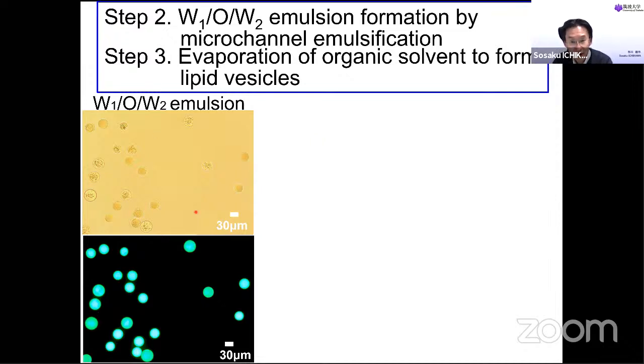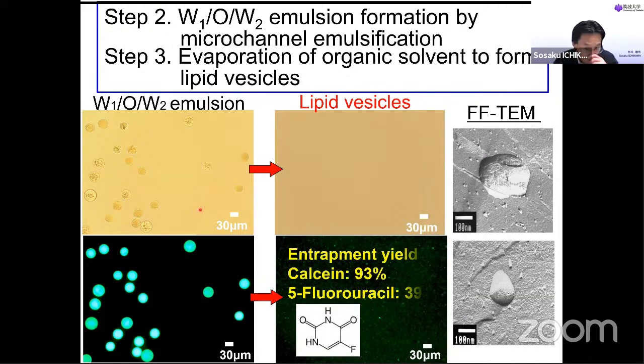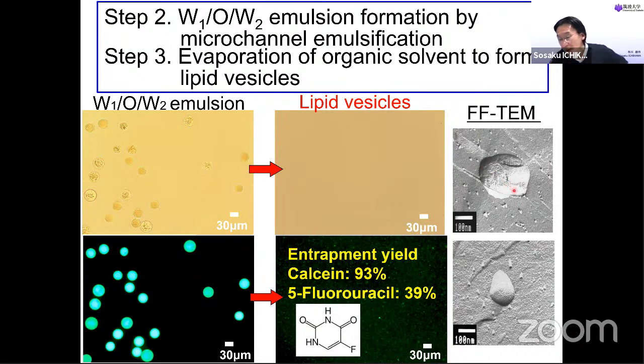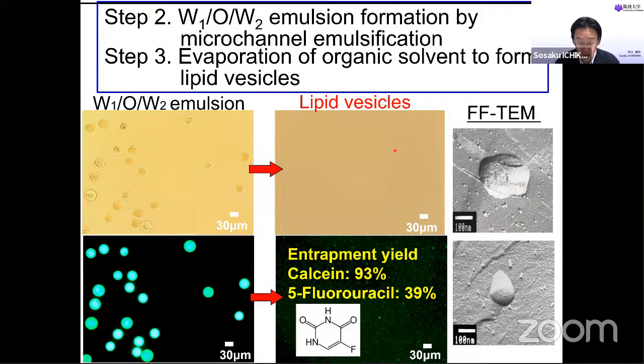This is the W/W emulsion. This is a lipid vesicle. We can observe the lipid vesicle formation by freeze fracture TEM like this. You can see the size of this lipid vesicle. The diameter is around 200 nanometer, so it's comparable to the size of the initial water droplet shown in the previous slide. The entrapment yield, for example, calcein as a fluorescence marker, is 93%.